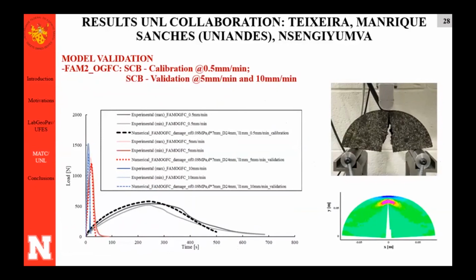So here it is. Now it has difference between numerical and experimental. Good. So we calibrated the 0.5 millimeter, which is the dashed lines. And I just put 2 results here from the experimental data that Laura has, but Laura did 5 replicates from each rate. And I just took the minimum and maximum and put here just to show, because we have variability in the laboratory as well. So we calibrate for the 0.5, and we use the same parameters to predict the behavior in other rates. And that's what we got, and that's what we got visually in the contour plot.